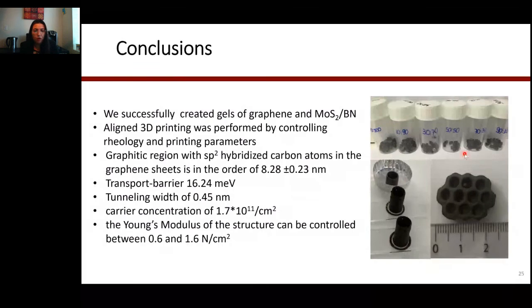As Leanne mentioned before, when we 3D print those gels, especially since we're making them ourselves, they need to be liquid enough to be extruded, while maintaining the shape of the extrusion. So there's a lot to play around with to have those structures large enough. In this case, even though it's much smaller than the talk that we had earlier today, it's still large compared to some of the materials that are done now with graphene and MoS2.